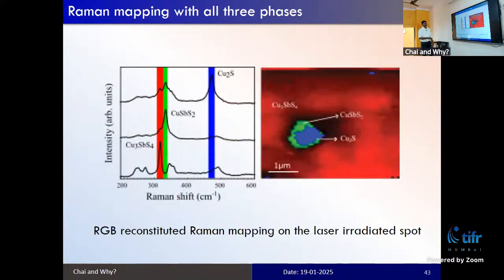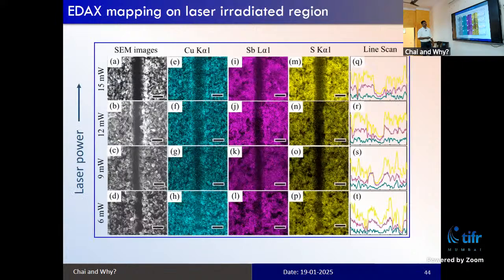We have done Raman mapping and a line scan of this material, so we have done an elemental mapping. We irradiated with different laser powers, for example 15 milliwatt, 12 milliwatt, 9 milliwatt and 6 milliwatt. You can see that there is a change in the diameter of the irradiated region also. We plotted the elemental composition, the different elements present in this material, and how they get evaporated. You can see sulfur is the easily melting material and it gets evaporated, and then there is antimony. You can see the line graph. In the laser irradiated region there is a material loss going on. These materials get evaporated and it tries to form a different phase.